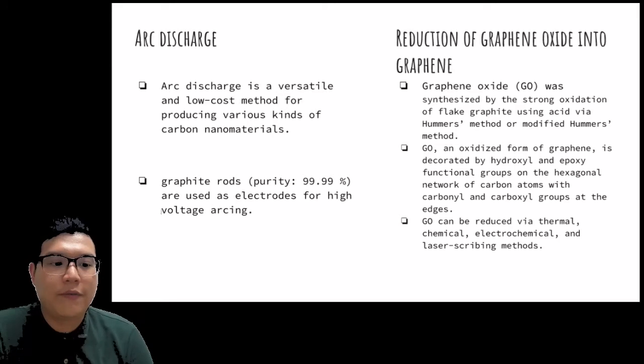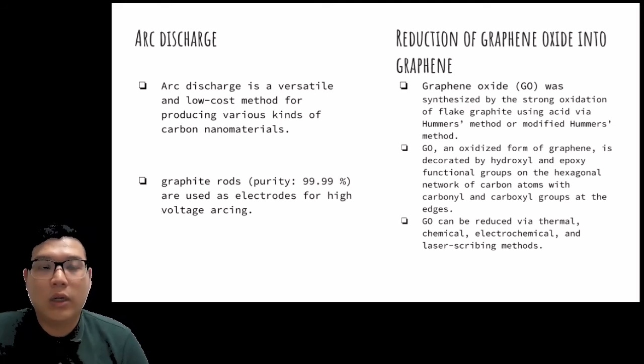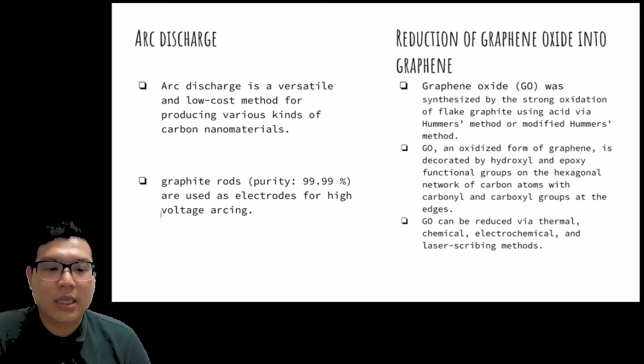To prepare pure few layer graphene, a direct current arc discharge of graphite evaporation was carried out in a water-cooled stainless steel chamber, now filled with different buffer gases after evacuating the chamber by a mechanical pump. When the arc discharge process ended, the generated soot was then collected under ambient condition.